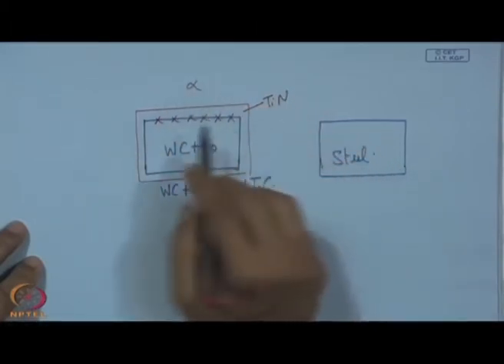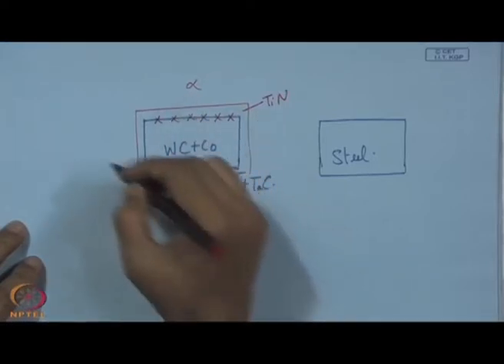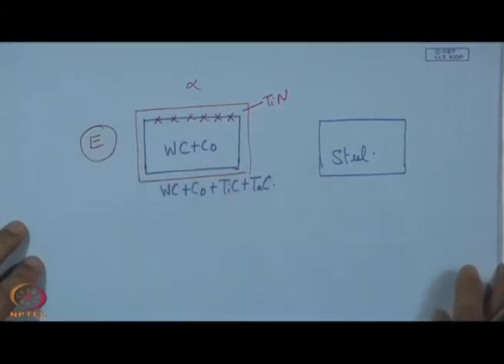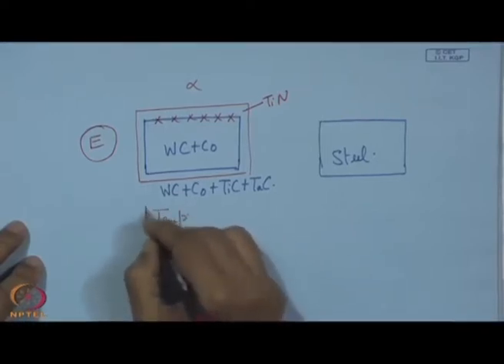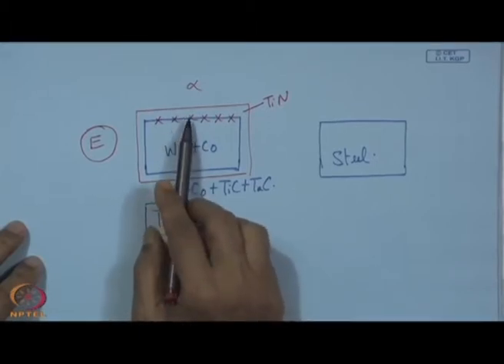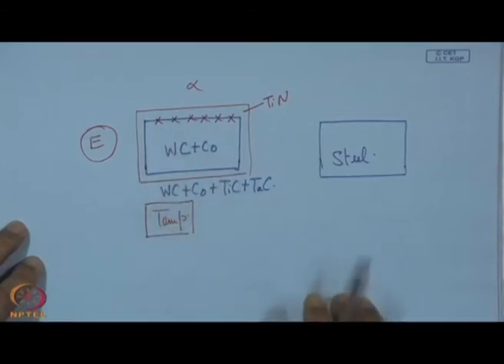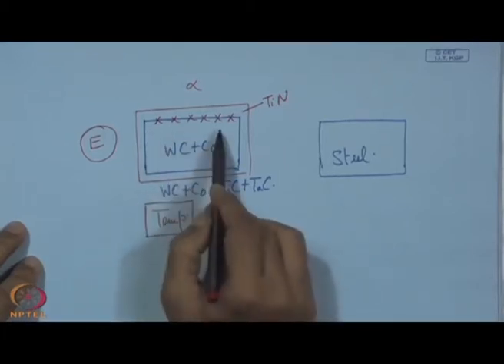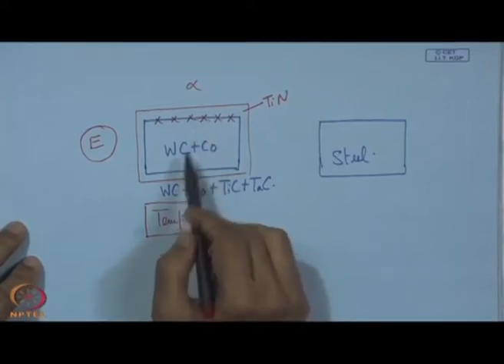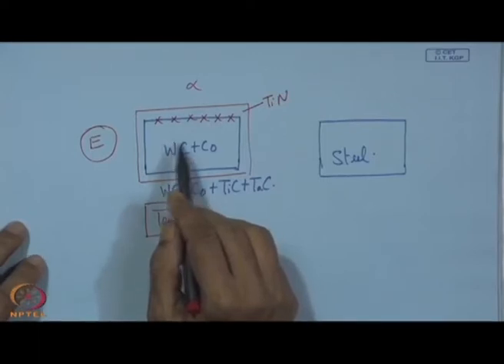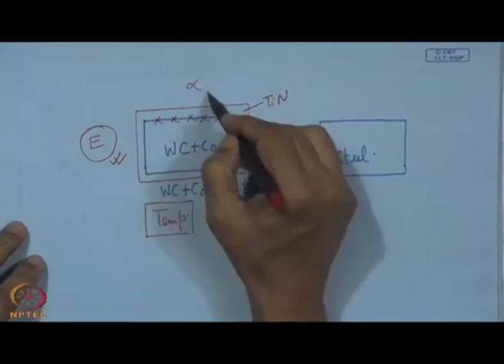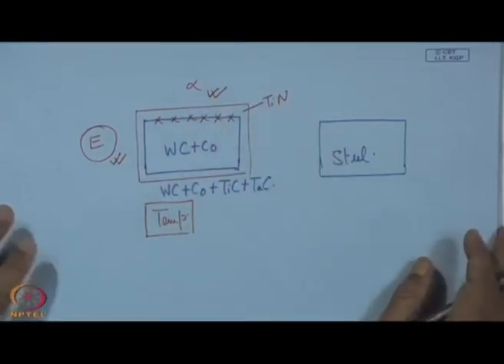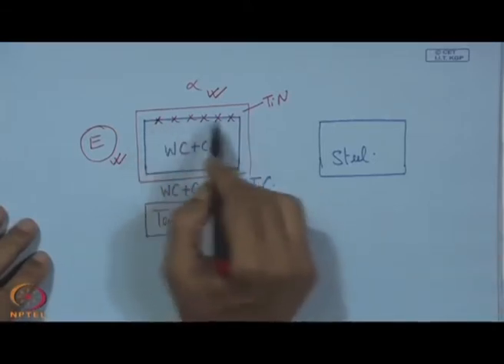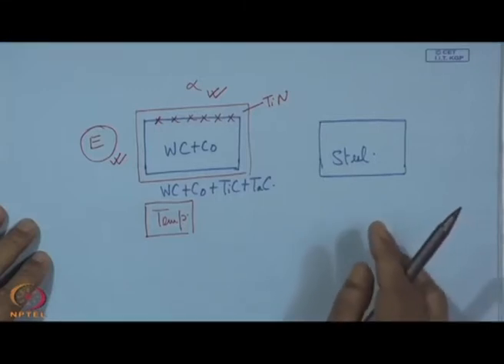So, their alpha value, the coefficient of thermal expansion, varies widely. The value of E, that means the Young's modulus, and then the deposition temperature, that is also very important. When it undergoes such treatment requiring high temperature and then has to be cooled down to room temperature, a lot of stress develops over this surface. Even if we have some chemical bonding, that advantage will be offset because of this wide variation in the values of E and alpha, which leads to residual thermal stress, and here we have breakage because of this stress development. So, at any cost this has to be stopped.